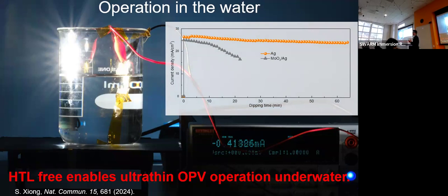The gray curve shows our conventional molybdenum oxide silver system. You can see the much improved water stability when using the silver system. Even after 60 minutes dipping into the water, the solar cell could be operated underwater almost normally.